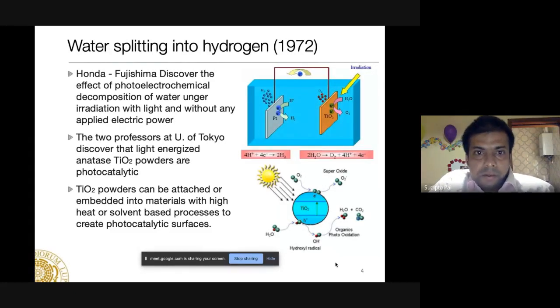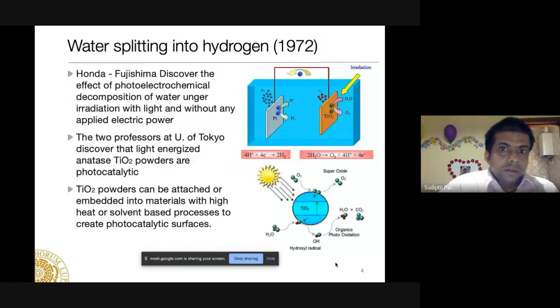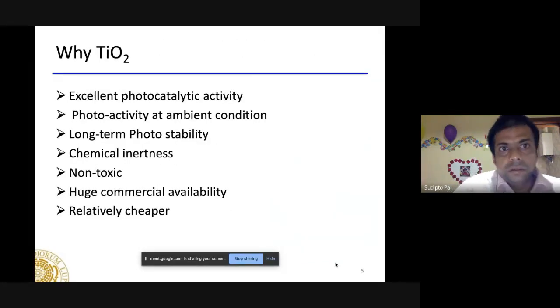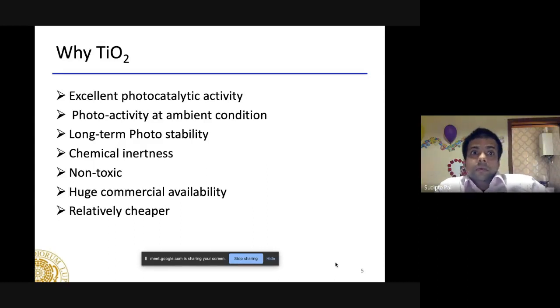Actually, this is the mechanism of the photocatalysis, and I have just shown one example with TiO2. There are several other photocatalysts in the market, and why I tell about TiO2 is because it's an excellent photocatalyst. It has excellent photocatalytic activity, and the photoactivity at ambient condition can be done. It has long-term photostability, and this point is one of the most important, because if one photocatalyst degrades after one reaction or two reactions, then it is of no use.